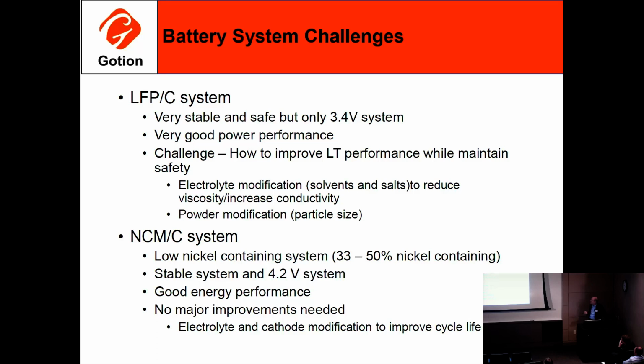And then the system on the bottom is basically NCM. Like I said, we're a couple years into that. This is the low nickel containing systems, up to the 523 type material, 50% nickel on the metal side of the cathode. It's a good system, higher voltage, 4.2, with good energy performance. Right now there are no real major improvements that need to be made with that chemistry. It's just increasing cycle life.